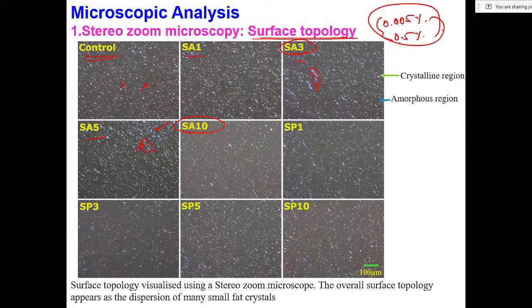On the contrary, if you look into the SP category of samples, where did we find at the initial stages? If you see, there are less crystalline structures. However, when we got into SP5 and SP10, they were having microstructures which were similar to, say, the control. So we can see when we have used emulsifiers of different HLB values, they are tailoring the structures of the fat crystals in a differential way, in a concentration dependent manner.